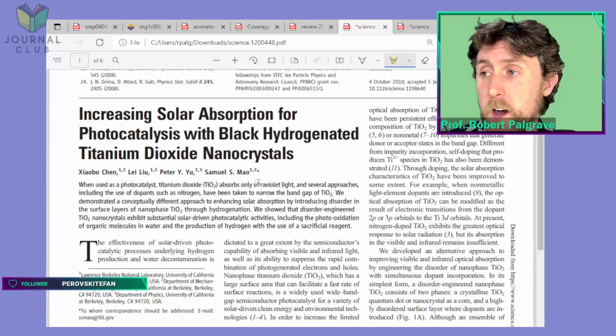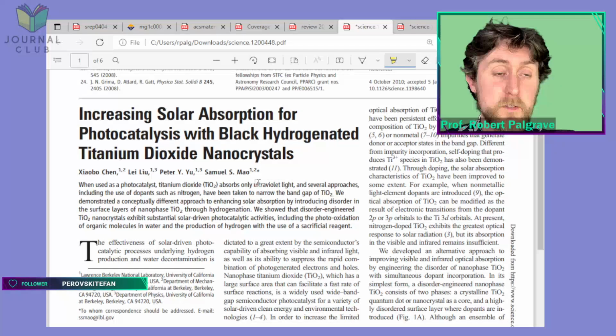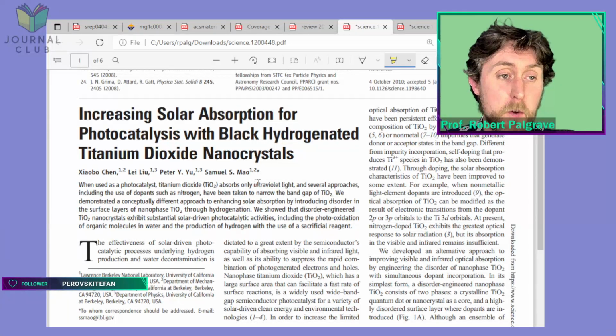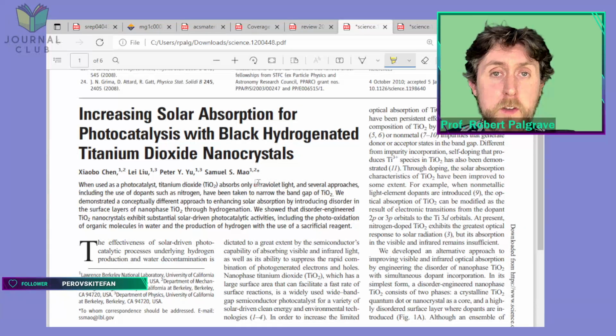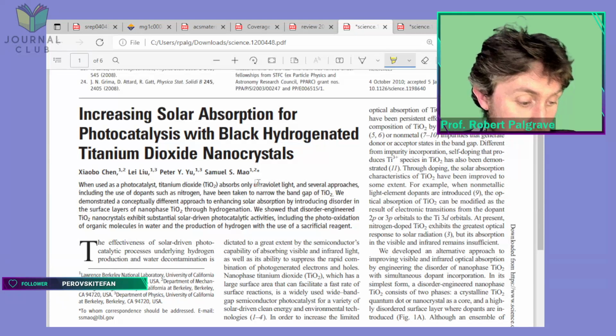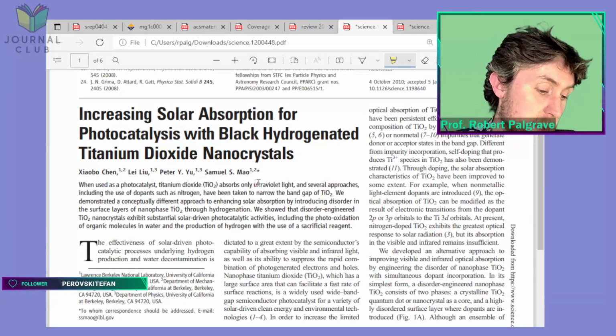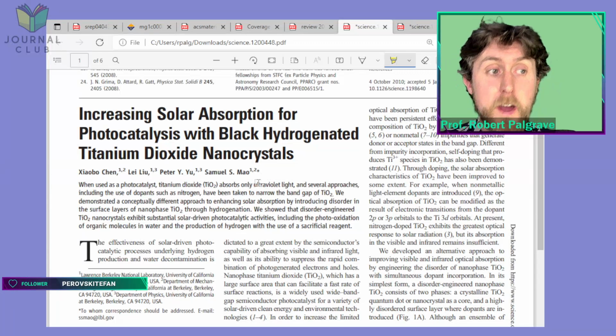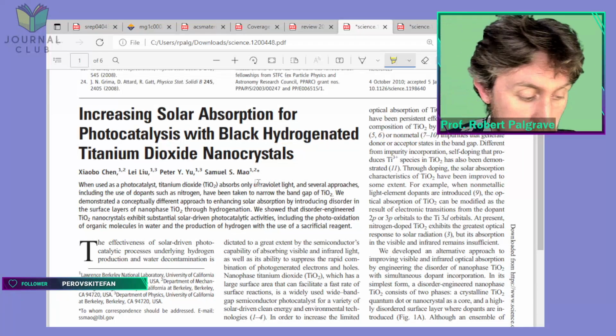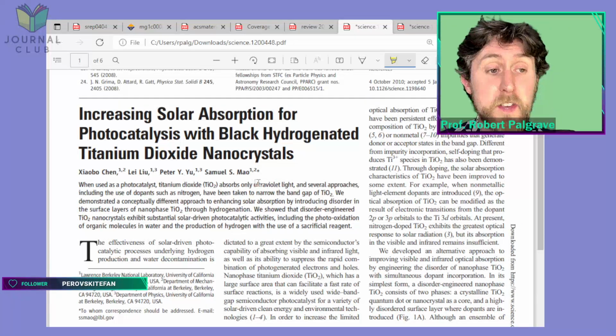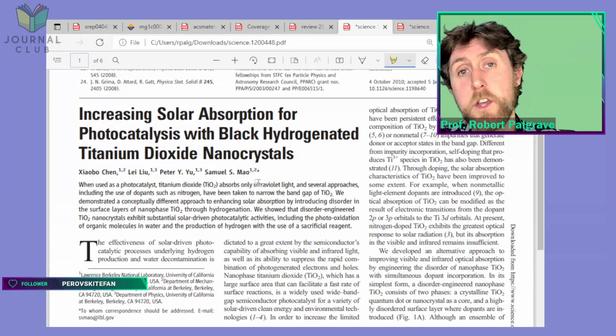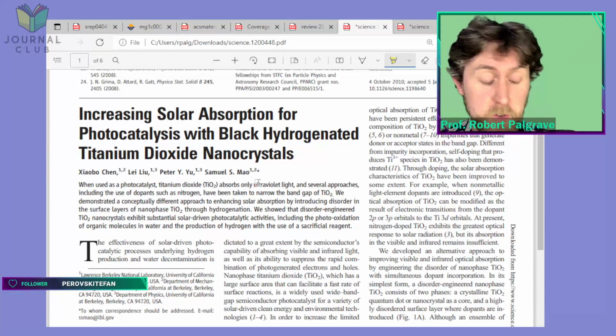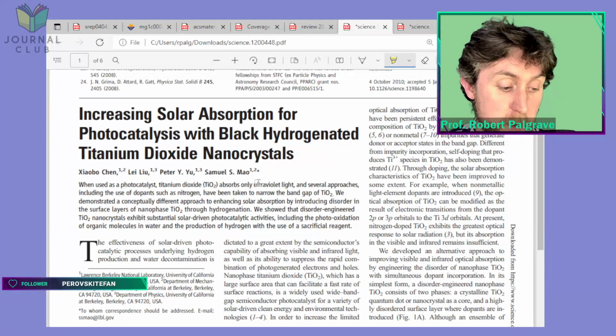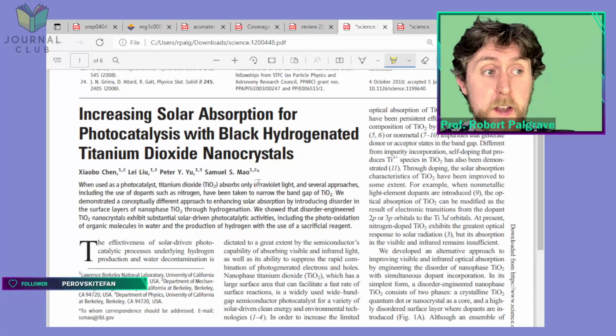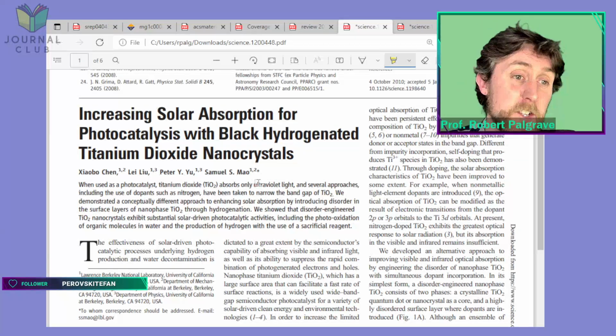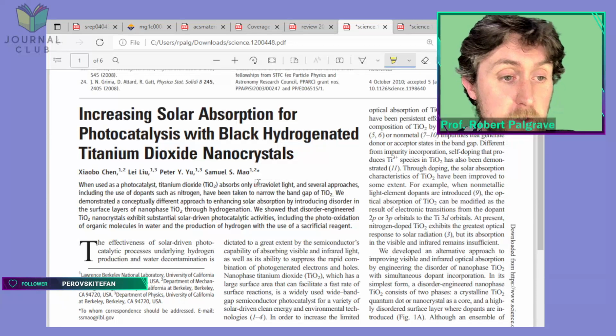And the big problem of TiO2 photocatalysis is that titanium dioxide itself doesn't absorb visible light, so it only works with ultraviolet light. So even though it has this really excellent catalytic activity, great potential for doing chemical reactions like water splitting to generate renewable energy, or even loads of other different chemistry on the surface of TiO2, this only happens in ultraviolet light. So if you want to use sunlight to split water into hydrogen and oxygen, TiO2 will give you very low efficiency, because it's only a very small part of the sunlight, the ultraviolet portion of the solar spectrum, that can actually be used to drive that chemistry, to do the water splitting.